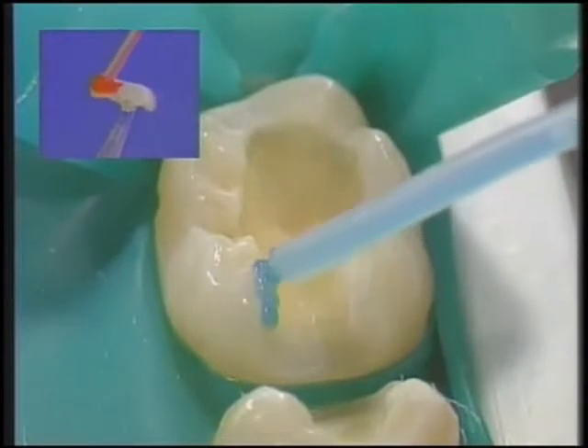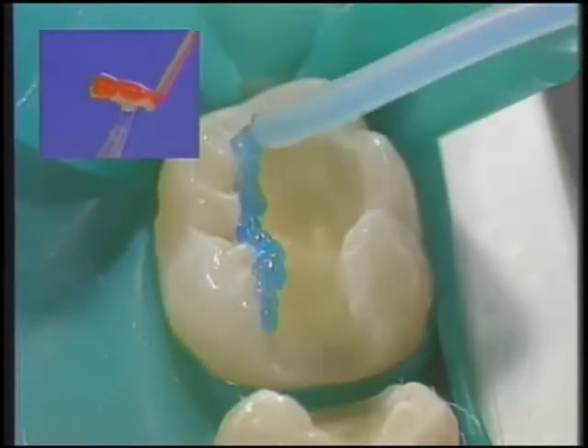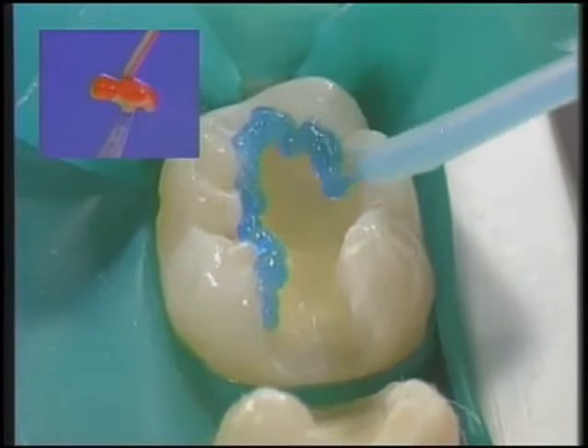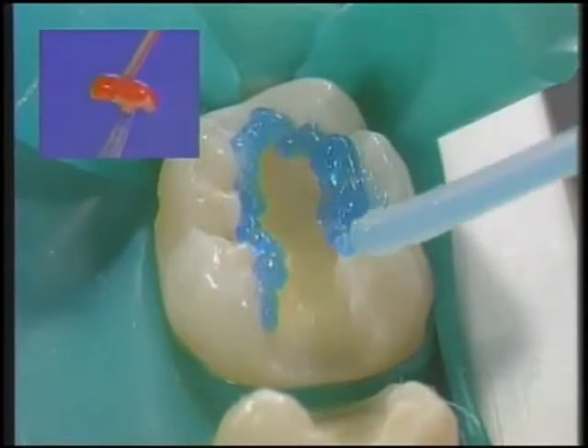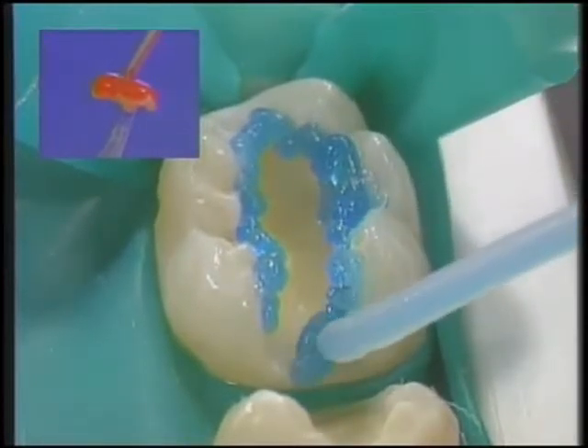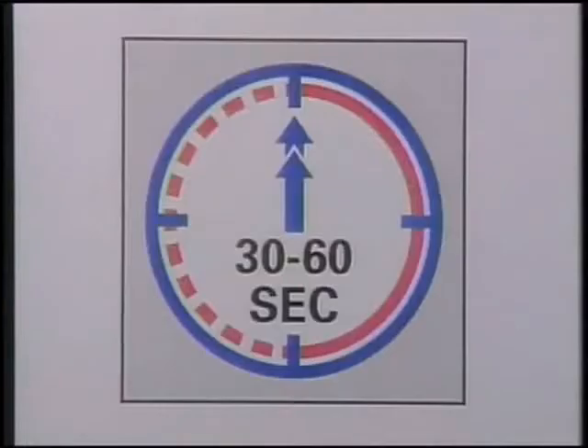The large picture shows the work directly on the patient. The upper left-hand corner shows the assistant's work. The tooth is etched with phosphoric acid and the inner surface of the ceramic with hydrofluoric acid. Tooth enamel should be etched for 30 to 60 seconds and ceramic for 60 seconds. The acid is rinsed off and the surface dried.